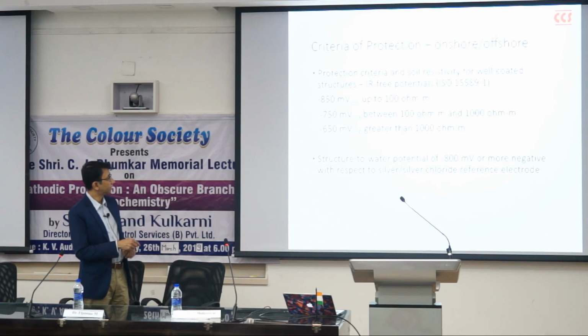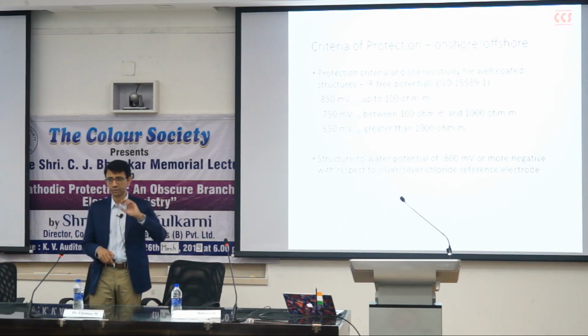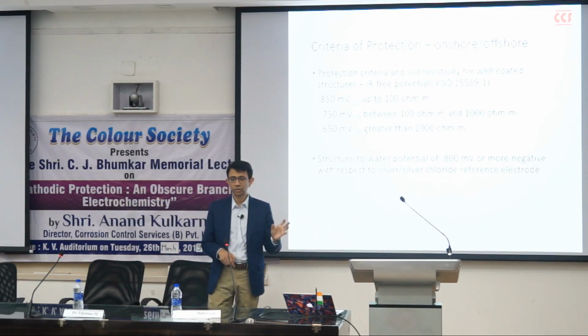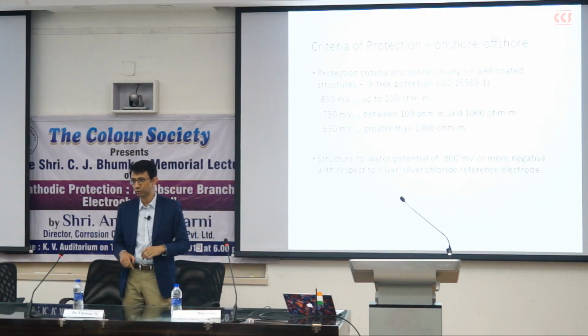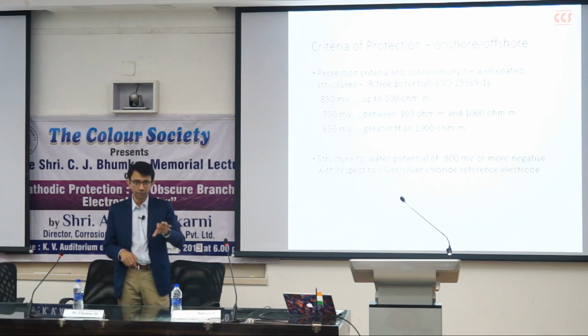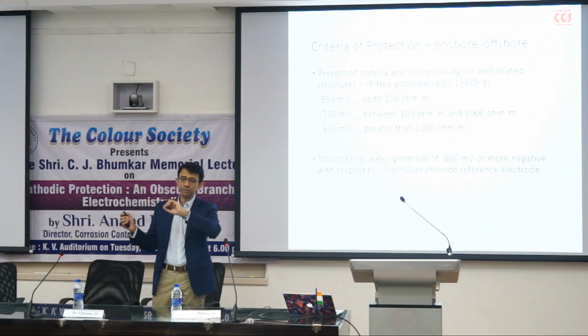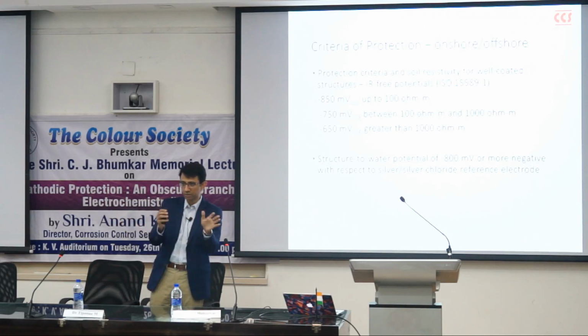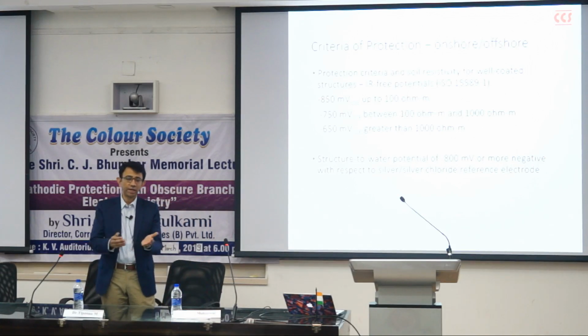In the ISO standards 15589, there are additional criteria which address the problem of resistivities. We must understand that as resistivities change, the chemistry of the soil changes. And cathodic protection, as we've seen, is making the structure the cathode of a cell. It relies primarily on the reduction reaction in which we have hydroxyl ions being produced. Obviously, when we have hydroxyl ions being produced, the pH of the electrolyte is going to increase. So cathodic protection is exemplified by not just a shift in potential, but also by an increase in the pH. They are concomitant phenomena. You have an electronegative shift in potentials as well as an increase in the pH.